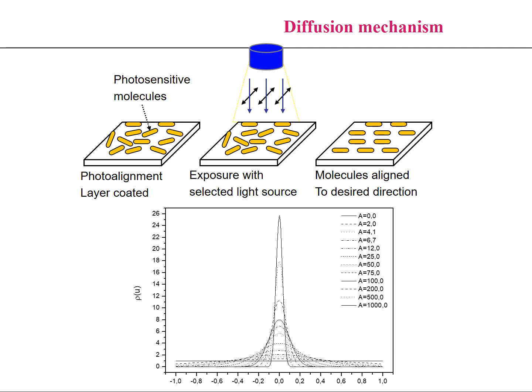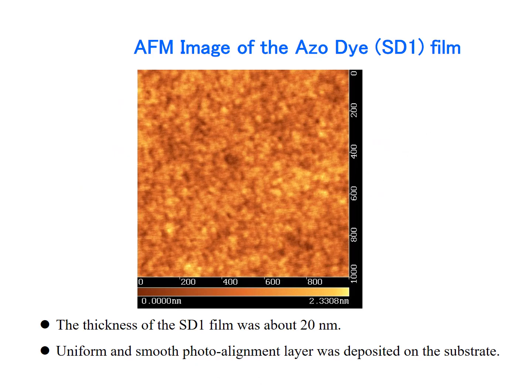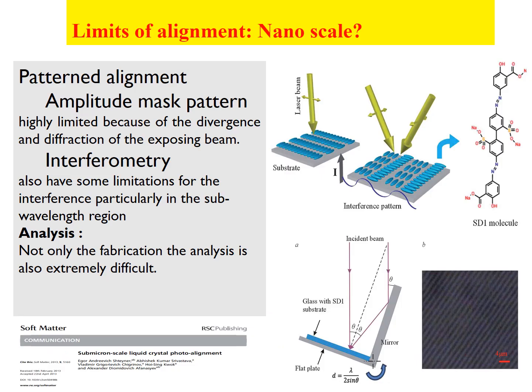So here is a picture of nanosize azo dye layers. The thickness of the azo dye nanosize layer is between 1 and 10 nanometers, and the molecules will rotate to become perpendicular to the polarization of the light. One molecule of the azo dye nanolayer on the surface will change the orientation of millions of liquid crystal molecules in the bulk. So here you will see the picture from the atomic force microscope, and you will see very uniform and high alignment.